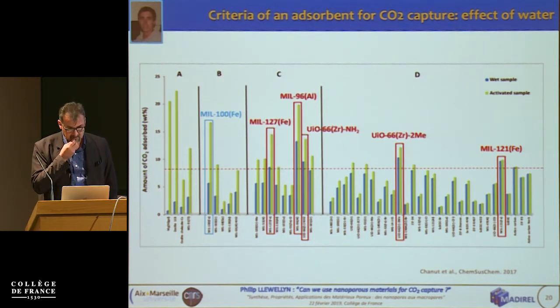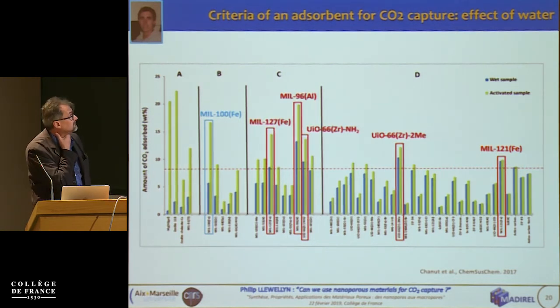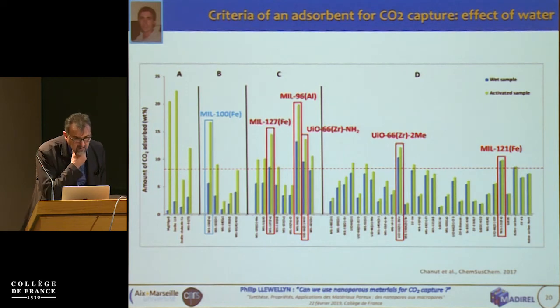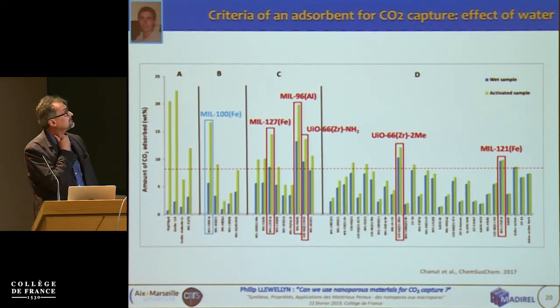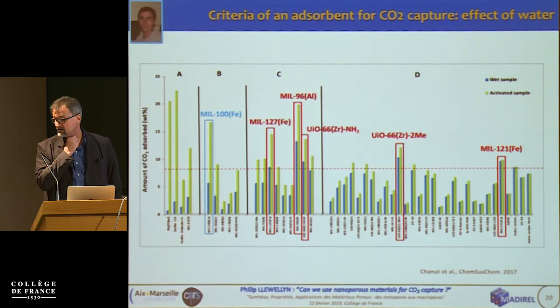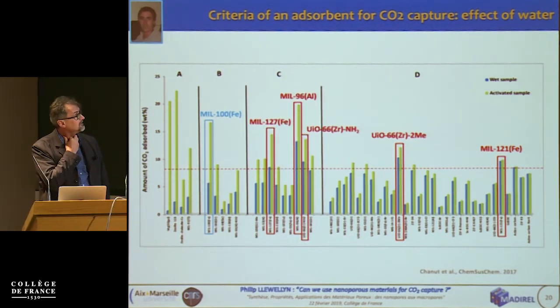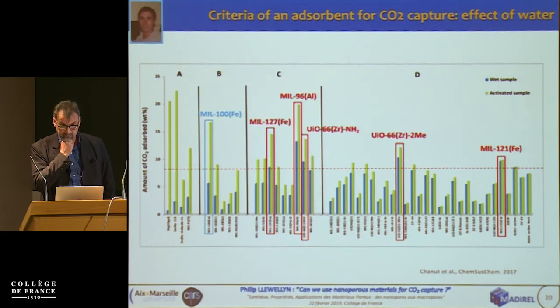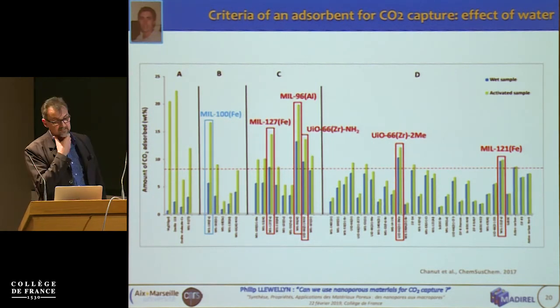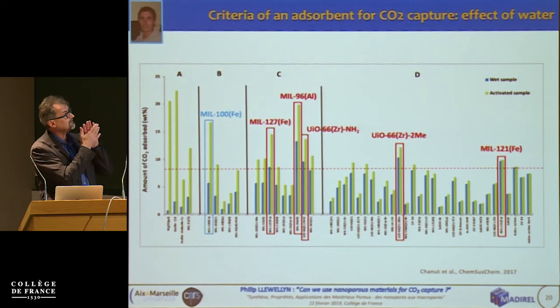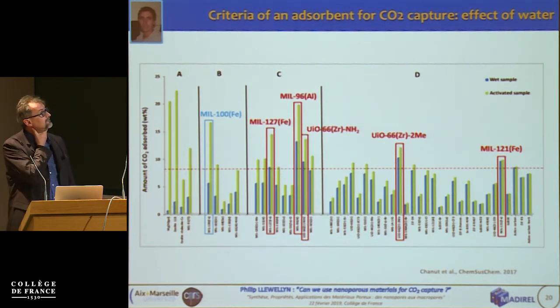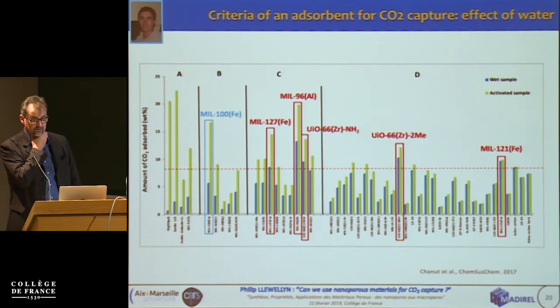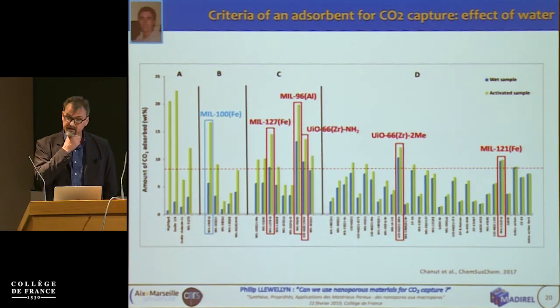So if we look on the left-hand side, we have one or two zeolites, and we can see in green a really good CO2 uptake. But in the presence of water, the uptake capacity decreases immensely. The blue is in the presence of water. Then on the right-hand side, we have a lot of carbons, and in between, we have a whole series of different MOFs. And there you have the names here. So we've picked out a whole series of MOFs which could be of interest for CO2 uptake in the presence of humidity.